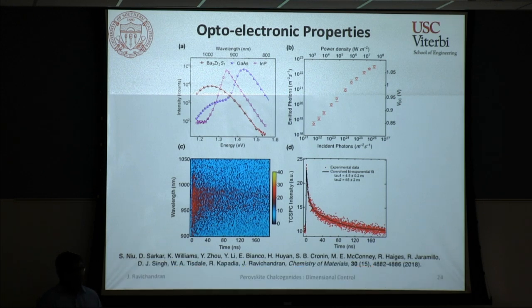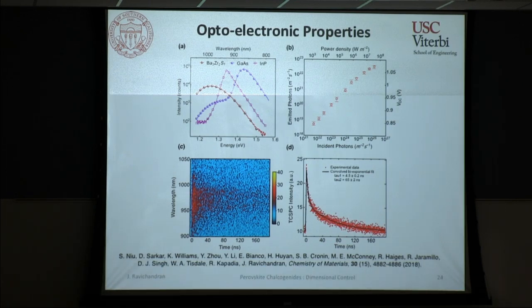And what we found, when we fit these time resolved photoluminescence curves, was that the lifetime was as long as 65 nanoseconds, which is actually pretty good, even better than some of the CIGS and CZTS materials that people have been studying. That tells us that if we make devices out of this, there is a very good chance you can achieve very high quantum efficiency as long as you can make optimized device structures. So this is just a precursor. It doesn't guarantee that your device is going to be highly efficient, but this is a good sign that you have good materials to make solar cells.